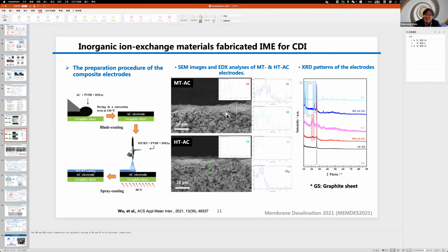It's a very good question. Compared to the stand-free membrane, the thickness of a normal membrane is about 100 micrometers, right? But when coating with this inorganic ion exchange material, could you see the slide? Yes, I can see that. Yes, you can see that the thickness is only less than 5.